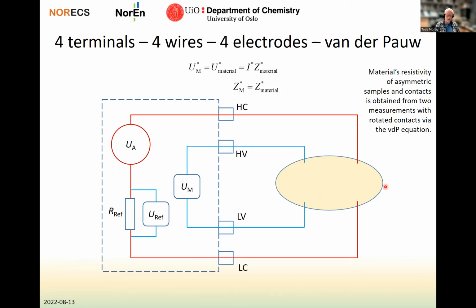Then you just have to do 2 measurements where you rotate the current so that you do the current through these 2, for instance, and measure the voltage through these 2. Then the van der Pauw equation does from these 2 measurements the correction of the geometry and gives you the proper disk material resistivity. This is something you can read about in papers from van der Pauw and others.